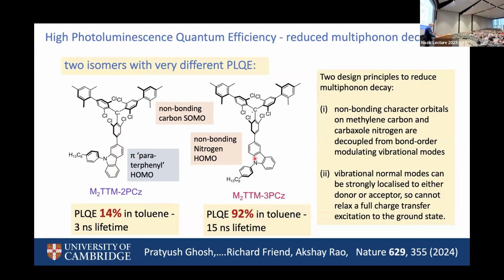The difference it makes is that the transition where we get high luminescence yield is from non-bonding to non-bonding. That is vibrationally decoupled, whereas whenever we use a pi or a pi star state, its energy depends on the bond order. If we change what is long and what is short, the pi and pi star levels go up and down. So when you do an optical transition, you can involve phonons, and those phonons can quench the luminescence. We can design in to get rid of the quenching and get really efficient luminescence, far, far redder than is usually possible for organic systems.